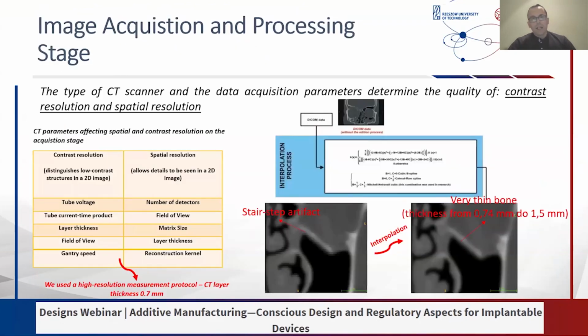So we start with the image acquisition and processing stage. We use a high resolution measurement protocol. The CT layer for this protocol is 0.7 millimeters. But the orbital bone is very thin, so the thickness is from 0.4 millimeters to 1.5 millimeters. So there are places where this thickness is very close to the value of the layer thickness.